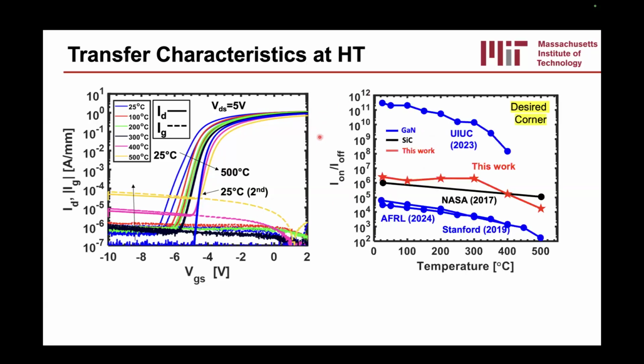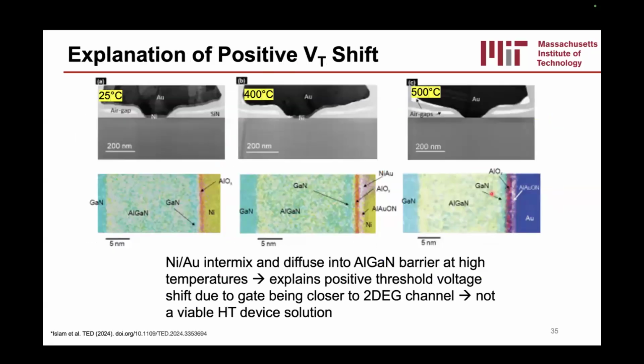And we can benchmark this on-off ratio, as many people do, for high temperature devices. And we can see that indeed we're able to get a relatively good on-off ratio across a wide temperature range, and better than a lot of the current GaN devices, and getting very close to the state-of-the-art silicon carbide devices made by NASA. Note this one right here is a HEMT that has 100 nanometers of aluminum oxide, so it's a little bit of an outlier to have a really low off current. However, we noticed that nickel gold is not the ideal high temperature material. As you saw, there was that permanent significant shift in the threshold voltage.